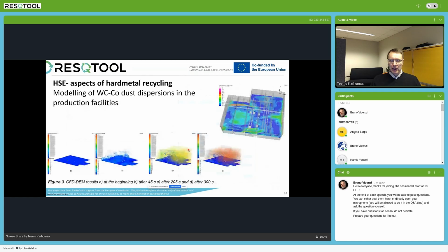And then we carried out computational modeling, where we measured all the airstreams coming in and leaving the production facility, and checked how that dust would spread with the airstreams. And we were surprised how high in the production facility the dust can go and how long it can stay in the air. And now we are thinking about measures to prevent the clean and dirty air from being mixed, so that we could keep some areas more clean where the employees stay, and remove the dirty air at some other areas.